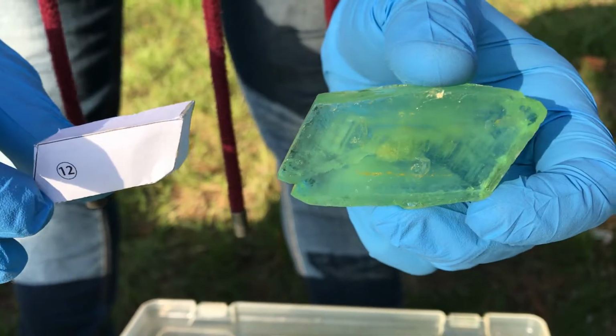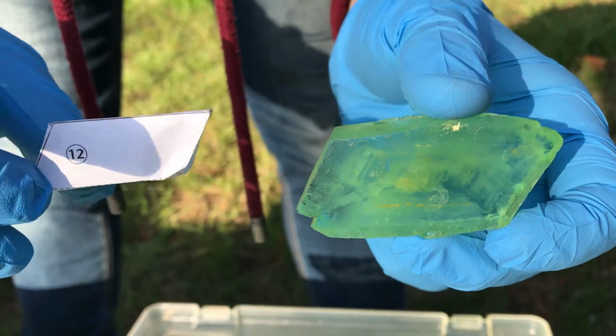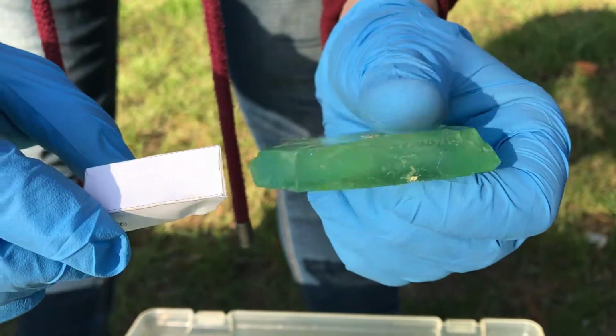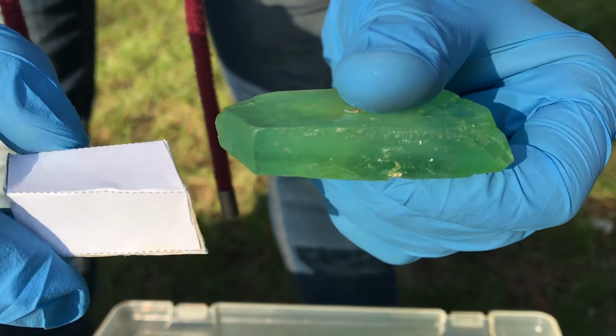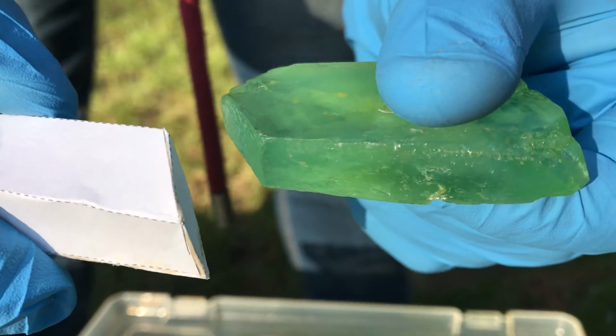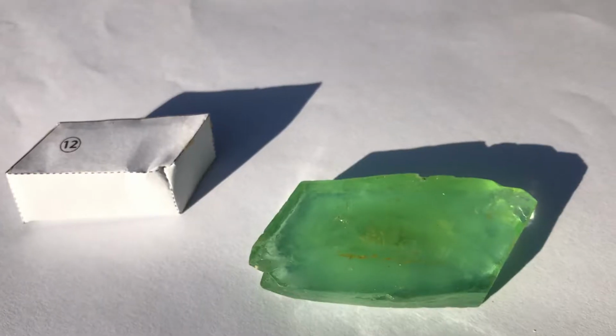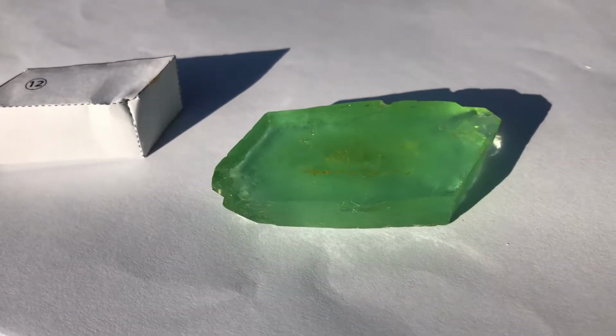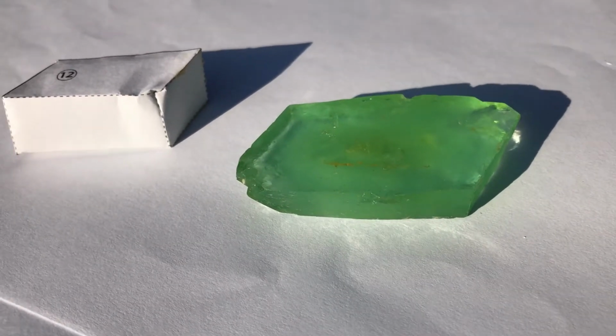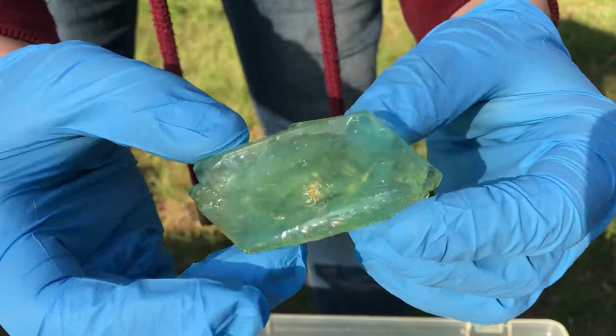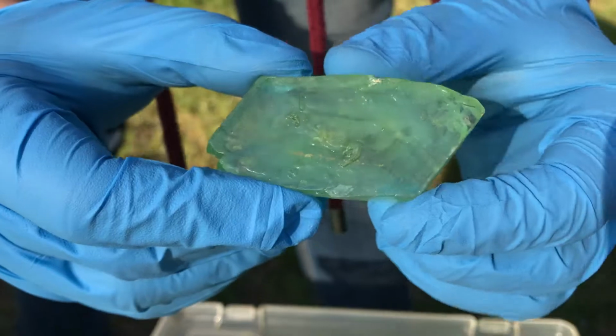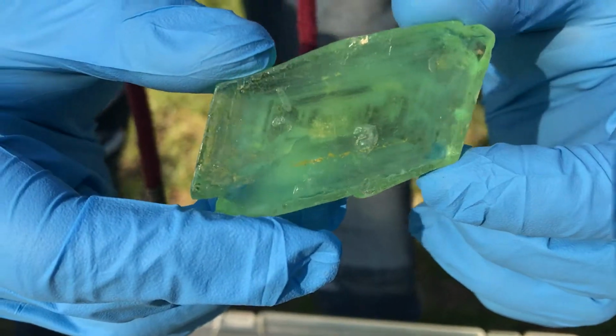We can see that some faces have irregularities and flaws. Also, the crystal is not fully transparent. All this testifies to the defects in the crystal. The defects in the crystal are due to the temperature fluctuations during the growth, the presence of dust in the solution, and the resulting iron oxide contamination.